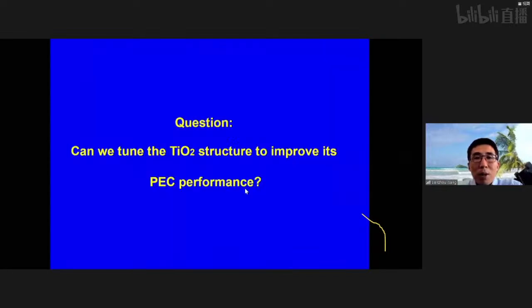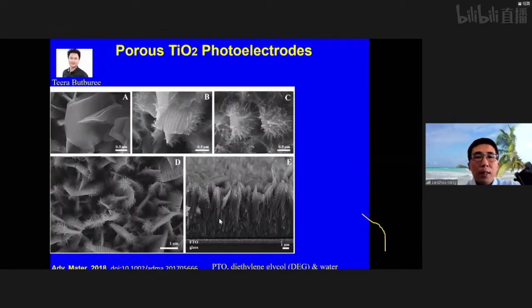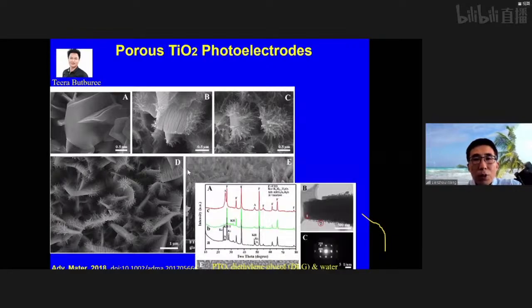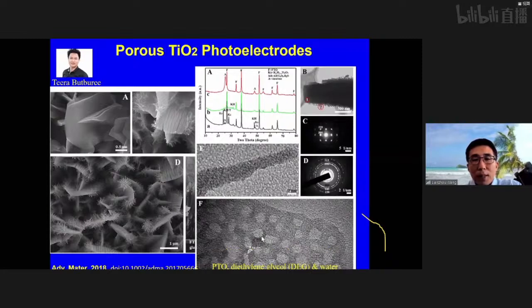And then the question came up: can we use the same material, TiO2, and by structure design improve the PEC performance of this material? So we changed the approach, still working on layered TiO2 materials, but we used a hydrothermal process to grow TiO2 nanoplates vertically on FTO glass, for example, in this case. We also found some interesting phenomena, because in this nanoplate there is a lot of porosity, and this can be very good because if you really want charge transfer and surface reaction in the photocatalytic process, the diffusion distance of the charge carrier can be very short if you have a lot of porosity.